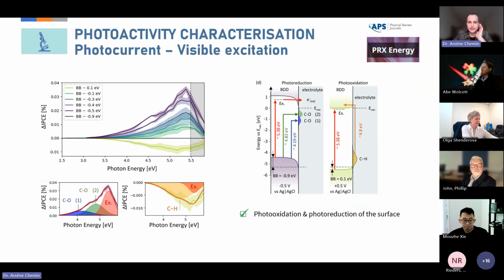So in this particular paper, no. We did see sub-bandgap photocurrent, but we were able to associate those photocurrents to the photoreduction and photooxidation of surface groups. And the only measurable solvated electrons we had were with bandgap photoexcitation. That being said, this was with boron-doped diamond.